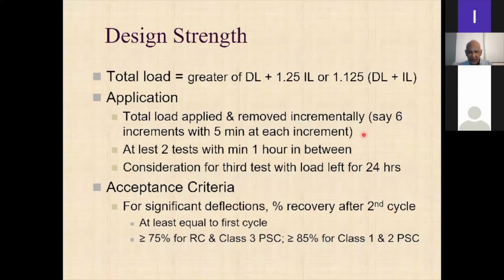The acceptance criterion is the percentage recovery of the second cycle. So you have a loading and then you unload, and you get what is called the percentage recovery. The percentage recovery after the second cycle should be at least equal to the first cycle, and it should be greater than 75% for RC and Class 3 PSC, and 85% for Class 1 and Class 2 PSC.